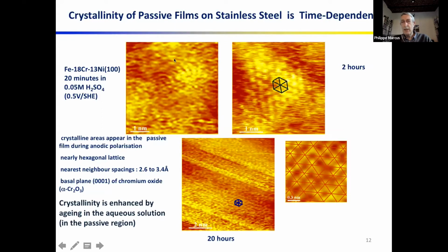And you can see that at the beginning, the surface oxide is completely disordered. It's amorphous. But when time goes on, we start to see small crystals, nanocrystals, because this is, again, high resolution, and this is an atomically resolved image. So nanocrystals are formed, and gradually the crystallinity extends, and the whole film becomes crystalline after long enough.